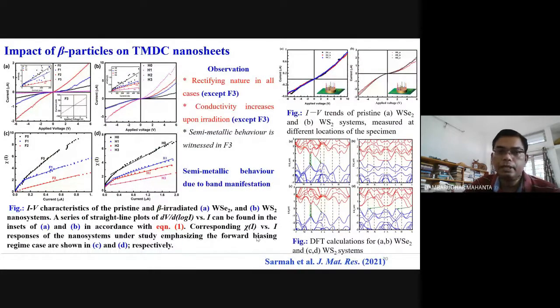Now, impact of beta particles on TMDC nanosheets. TMDC nanosheets means, again we'll emphasize only WS2 and WSe2 systems. In this case, F0, F1, F2, F3, all these are for WSe2 systems, H0, H1, H2, H3 for WS2 systems. And this was a very simple experiment: you have a beta source in an MSc lab. So we have exposed our sample for some days and calculated the dose, and after that measurement was done using two probe contact using 2400 source meter of Keithley.